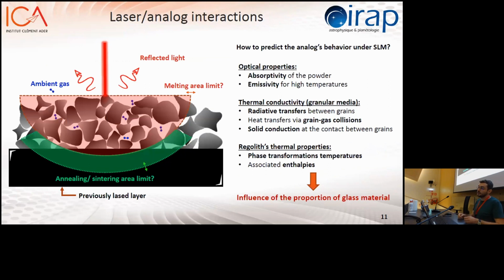So now we want to understand how the process in itself interacts with the powder. And so the first question we have to ask ourselves is how much of the quantity of energy I'm bringing with the laser is actually absorbed by the powder. And so that's all about the optical properties that you are familiar with, like the absorptivity, and then for higher temperatures above 1000 degrees, all the emissivity aspects. Then you want to know how quickly and how far the heat you are creating will be conducted in this granular media. And then, of course, finally, you also want to know at which point your material is actually going to melt and what kind of crystalline structure you can get at the end of the process.